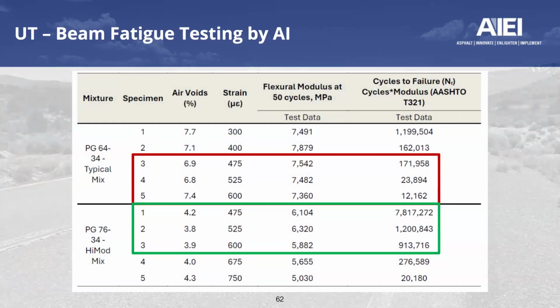We did acquire some of the Utah mix, again, from the Beck Street facility, utilizing a proven 64-34 superpave mix and comparing that in beam fatigue to the highly modified option at low air voids. And you can see that in the boxed examples, we are looking at equivalent microstrain requirements of 475, 425, and a peak of 600.